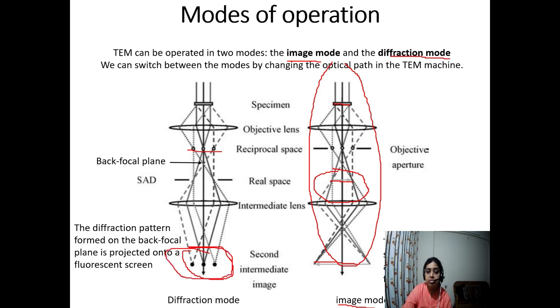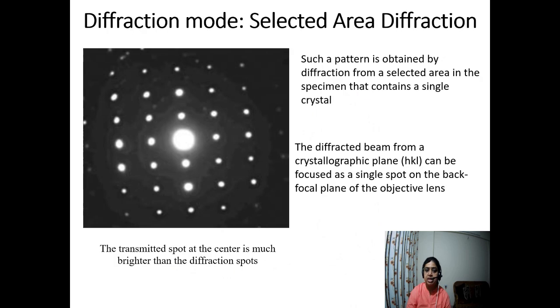So this kind of dotted pattern we get. So this is basically diffraction mode. Can you see this spotted pattern? Suppose your sample is crystalline in some area. We just focus, select that area, and we get this kind of selected area diffraction pattern. From here we can get a lot of structural information, like lattice parameter, lattice spacing, d-spacing, and phase formation. Even if you have some defects in the crystal, that can be estimated from this diffraction pattern. This kind of pattern can be obtained if we focus the back focal plane over the fluorescent screen.